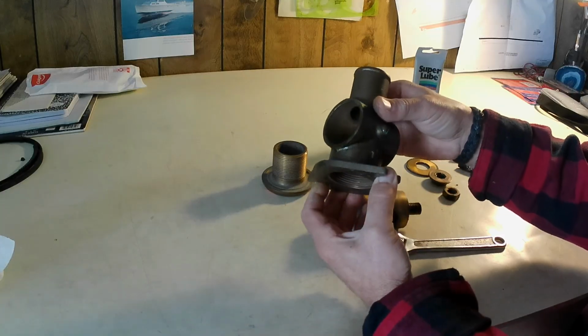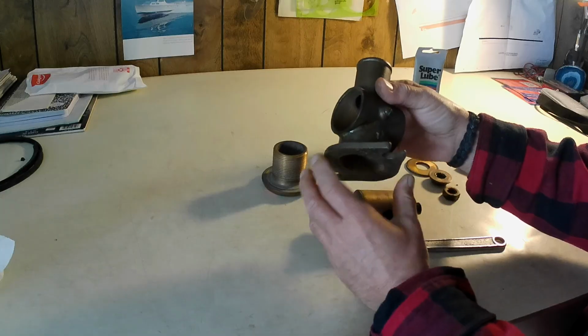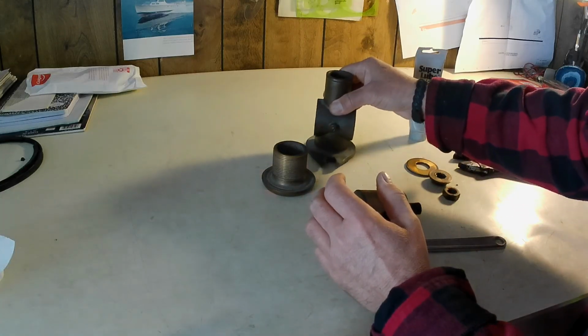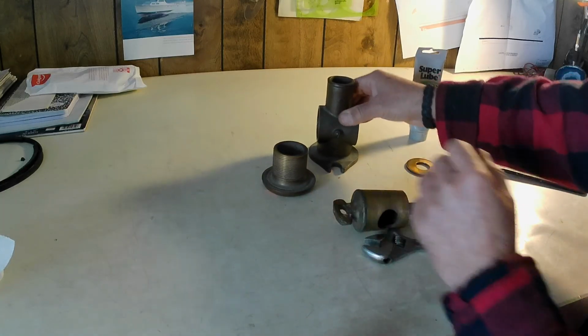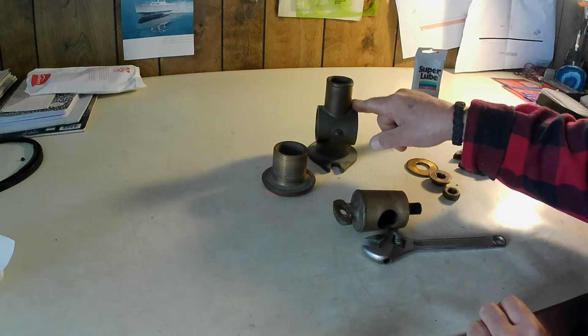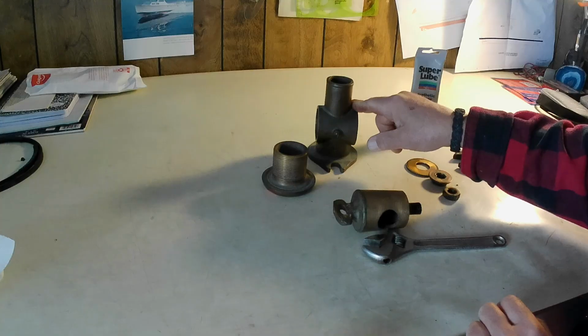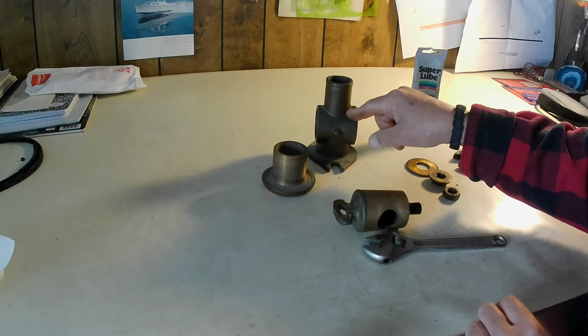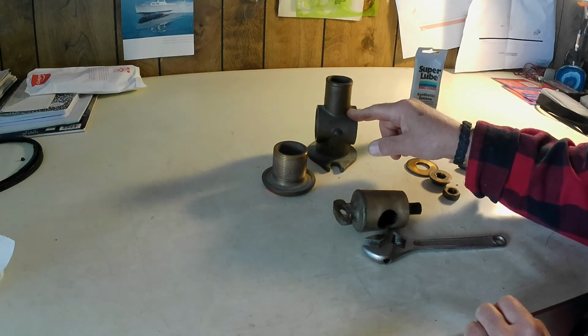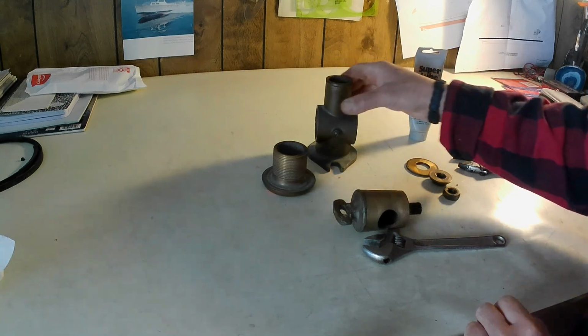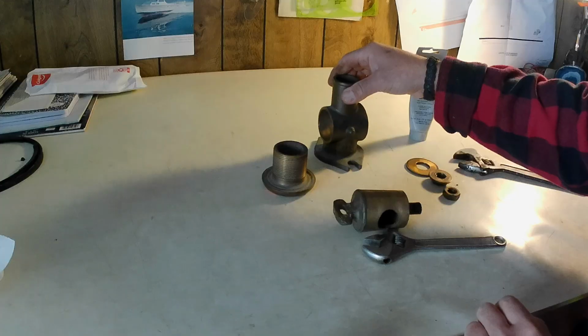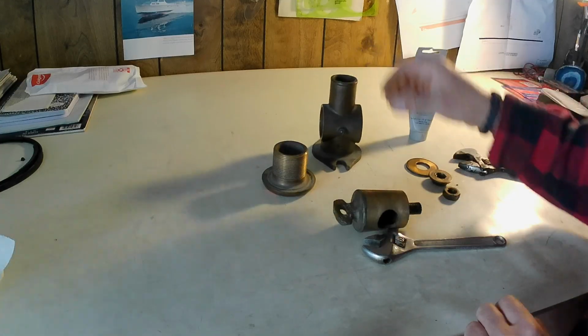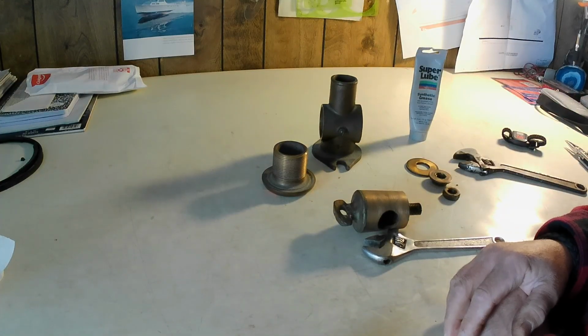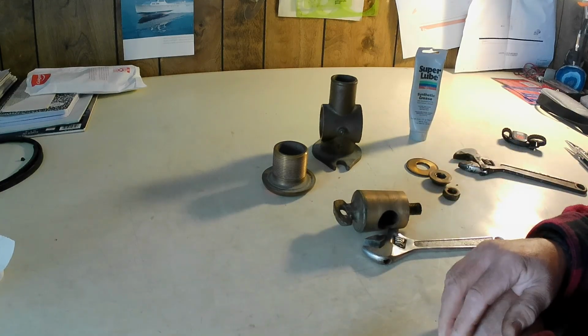It's not guaranteed that it's going to blow out of the hull. It's not guaranteed that it's going to crack and crumble after, but putting that much power through this as an electrical conductor will certainly render this in need of replacement, and could very well heat up the area around this to the point of damaging your fiberglass and your paint. So lightning strike's probably one of the biggest critical downsides to bronze.